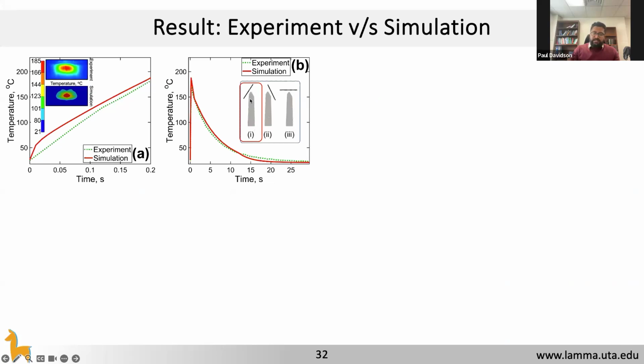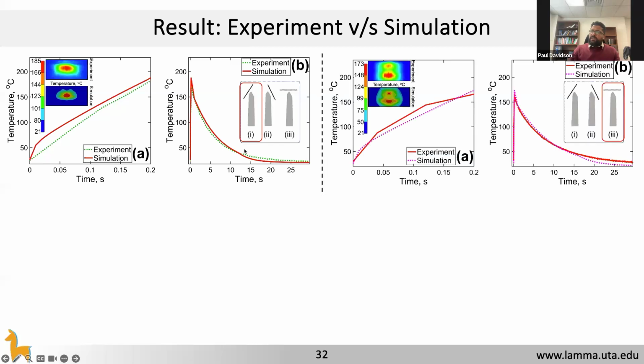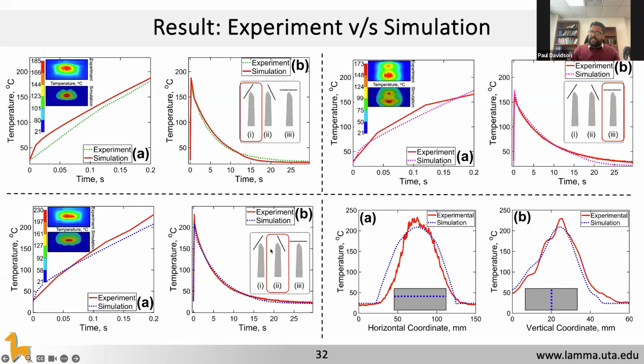So this is for facet 2. This is for facet 3, which had a very complicated irradiance profile. Both the heating and the cooling match up quite well. And these are for facet 4. So here the heating matches up very well with the experiment and so on.